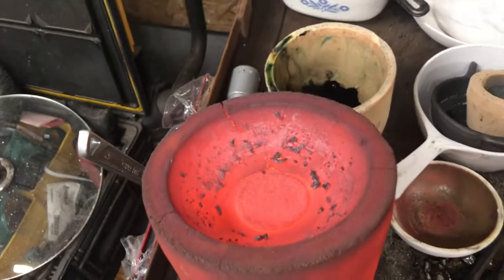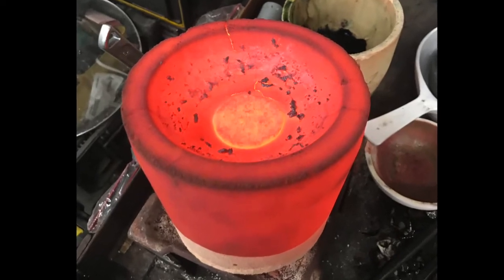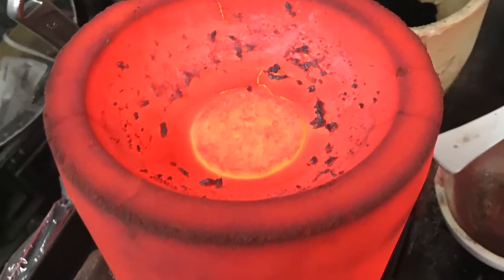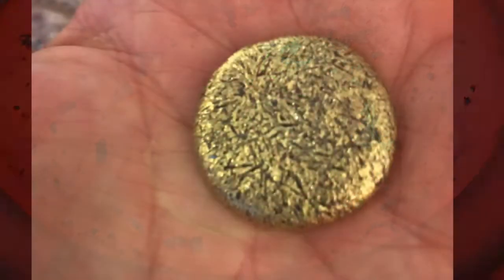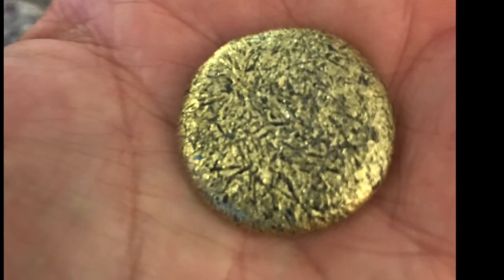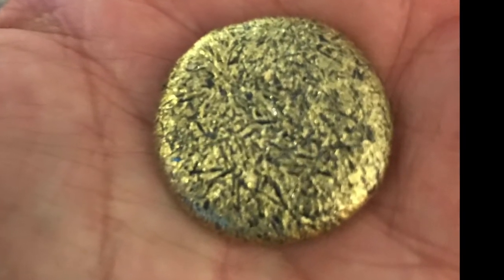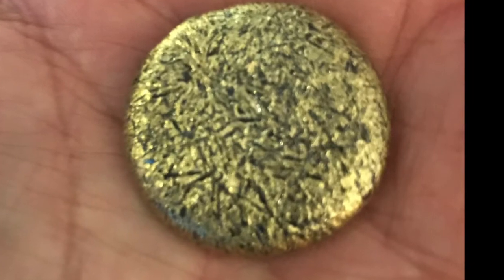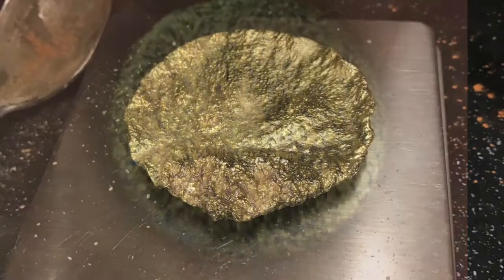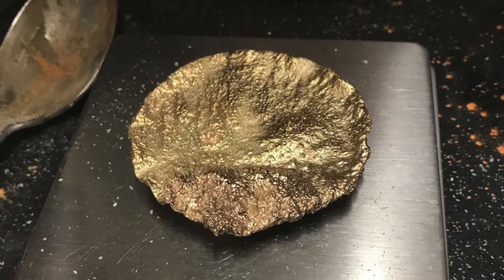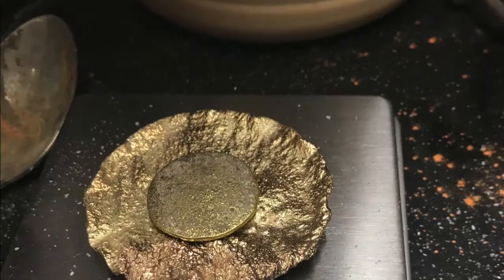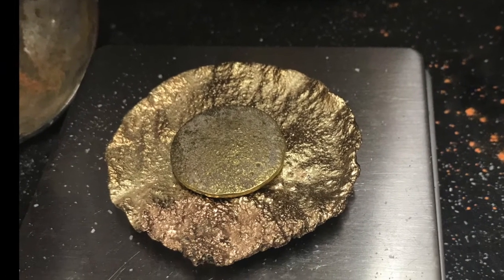That'll get cleaned up. Typically we were looking at about 40% gold purity, a little more than that in copper, and a small amount of silver. In order to have a nice consistent bit of gold to sell to the buyer, that needed to be refined a little bit more.